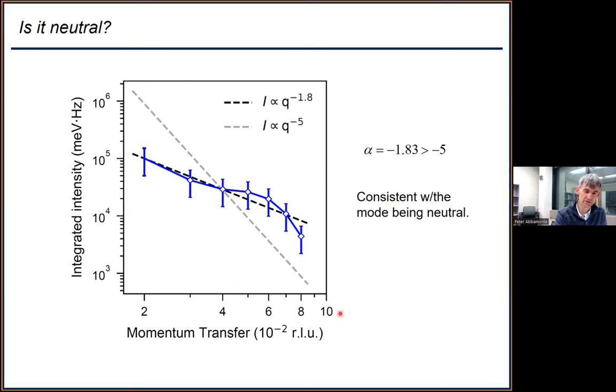This is transferred momentum Q on a log scale. This is integrated intensity on a log scale. So it's a log plot, so power laws show up as lines. 1/(q^5) is the dashed line. And what the data do is something with a significantly smaller power than that, meaning less negative. It's actually close to q^-1.8. And -1.8 is significantly greater than -5. That's consistent with the mode being neutral. So it's gapless. For a charged mode to be gapless, it has to be neutral. And it turns out if you check it against the sum rule, it's also consistent with it being neutral.